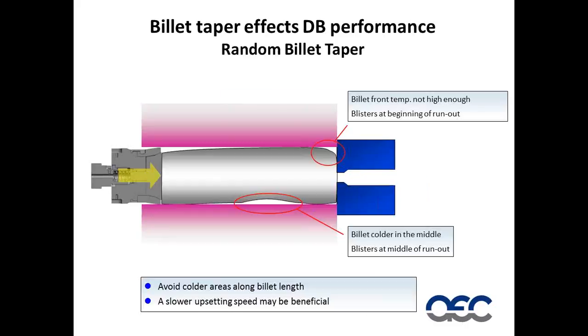I was actually at an extruder 2 weeks ago, and I hadn't seen this before, that they're heating their billet sideways. So they were heating it from the front and the back end of the billet. And in all cases, the center of the billet was cold. When we have this problem, we're actually going to start crushing from both ends and to trap gas in the middle. Again, the dummy block can only help you with gas that's at the back end of the billet. The rest of it is also all process management.